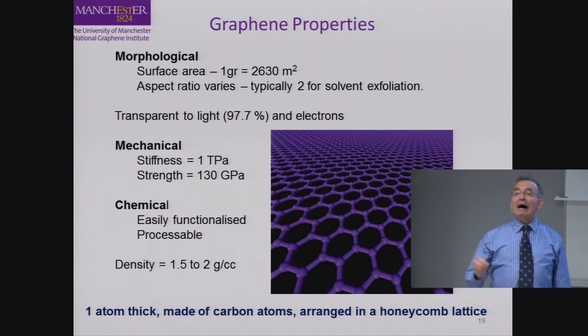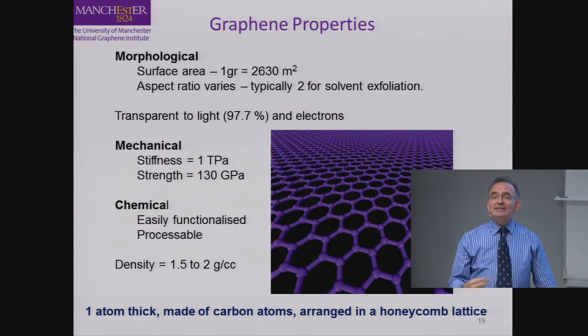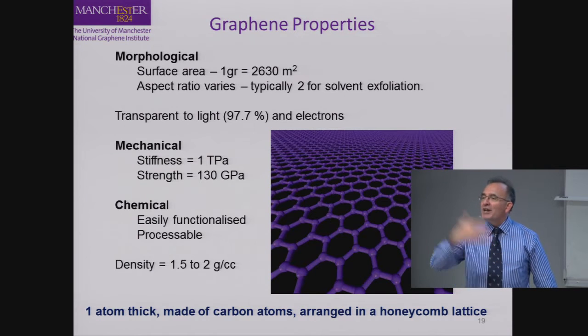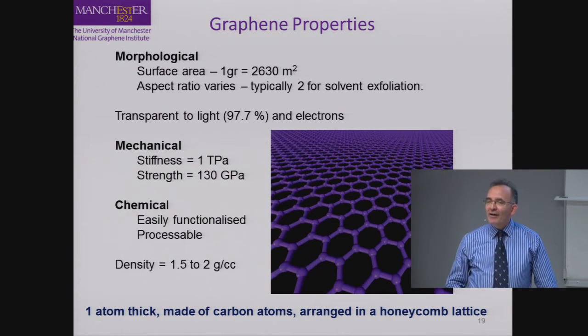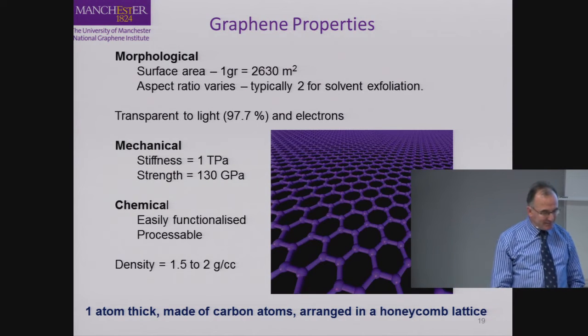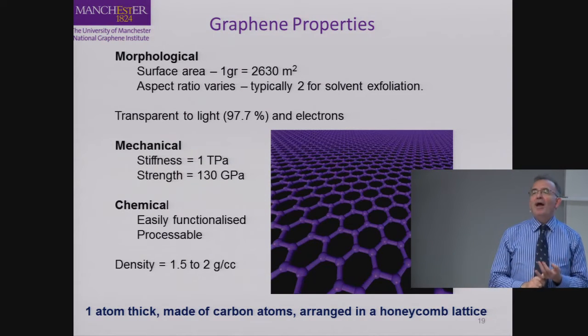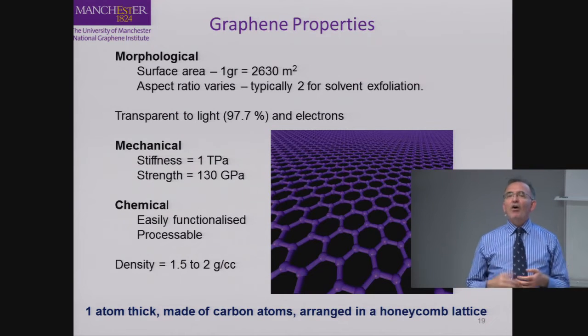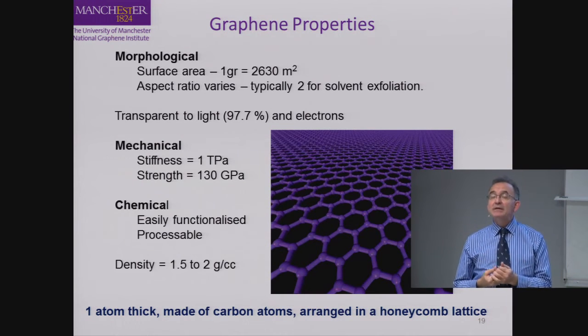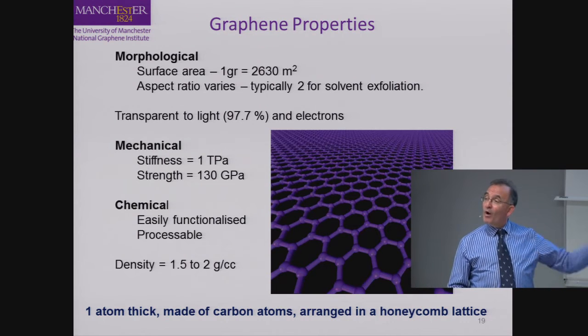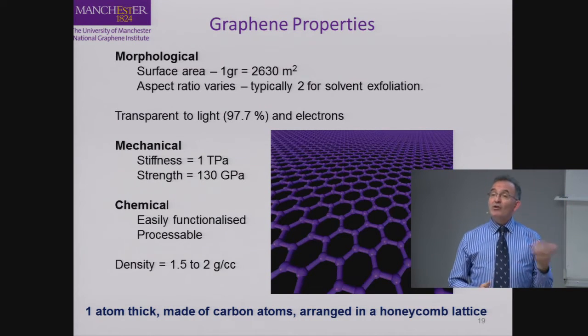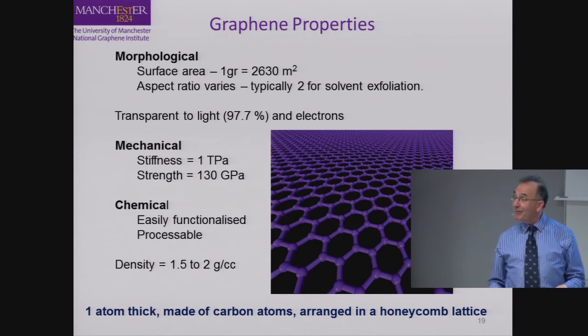And if we look at some properties like stiffness, it's in the region of 1 terapascal. And if we look at strength, it's 130 gigapascals. While if you compare the stiffness of currently used carbon fiber systems, the stiffness of carbon fiber is in the region of 250, 300 gigapascals, while here we're talking about 1,000 plus gigapascals. And if we look at the strength, carbon fiber is in the region of 2.5 to 3 gigapascals, while here we're talking about a strength of 130 gigapascals.